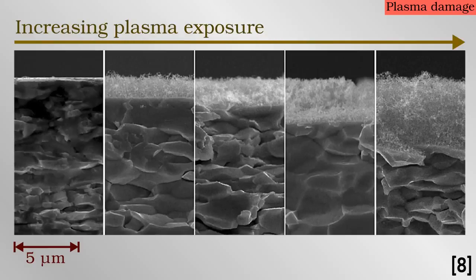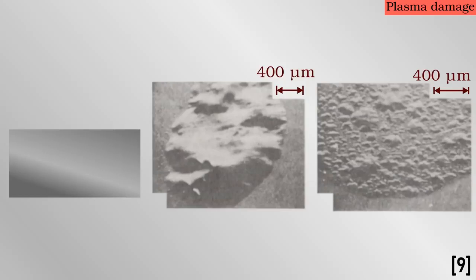Under the influence of incoming plasma, materials such as tungsten turn to fuzz, this is a technical term, as shown here in images from an electron microscope. Ions originally from a plasma can penetrate some ways into a metal and recombine back into a gas. This gas will coalesce some distance below the surface and create blisters to further damage the first wall.